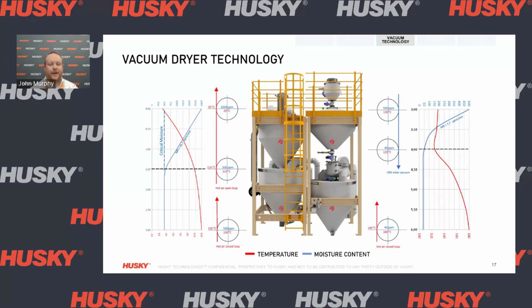When we look down in the bottom left-hand corner in stage 2, there is no moisture removal. We see it steady, but we do see an increase in temperature where we're increasing from 100 degrees to 130, 140 degrees. From there, the material is transferred to the vacuum stage, or the top right-hand side of this graph.